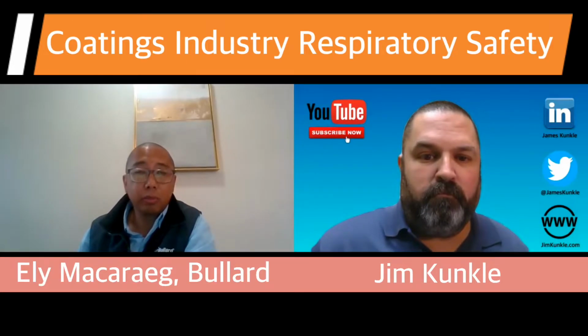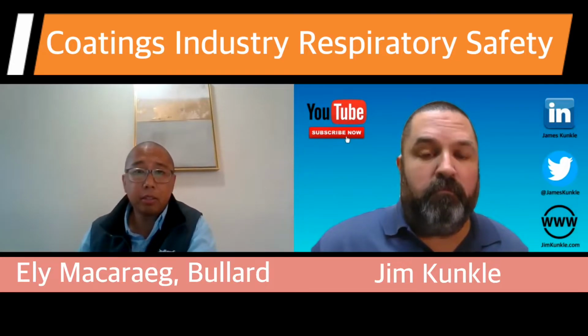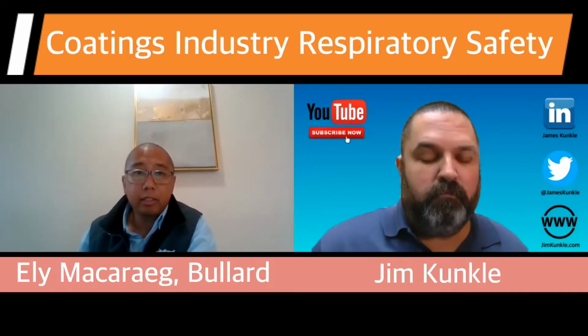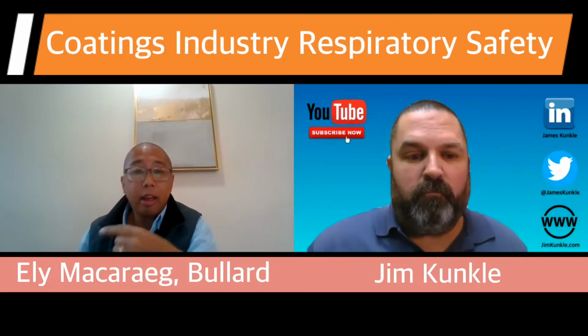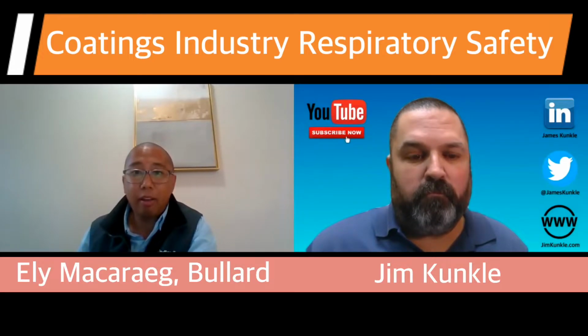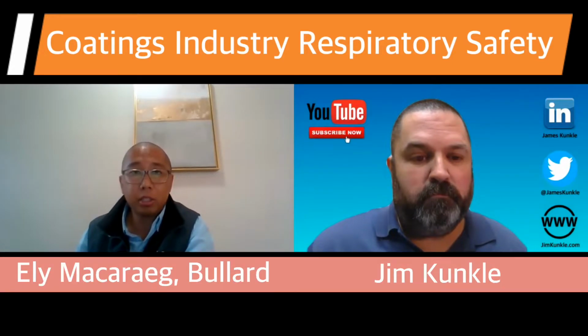Mm-hmm. And looking at the sources of where that comes from, you can pretty much say they come from three primary sources or contributors to those types of toxins. The first is the base material that's being blasted. So you're looking at things like steel, aluminum, copper alloys. A second potential source of contaminants is the surface coating itself. You have your pre-construction primers, your anti-corrosives. In the shipyard industry, you have anti-fouling paints. Concrete and cement can actually fall under the first category of the base material that's being blasted.